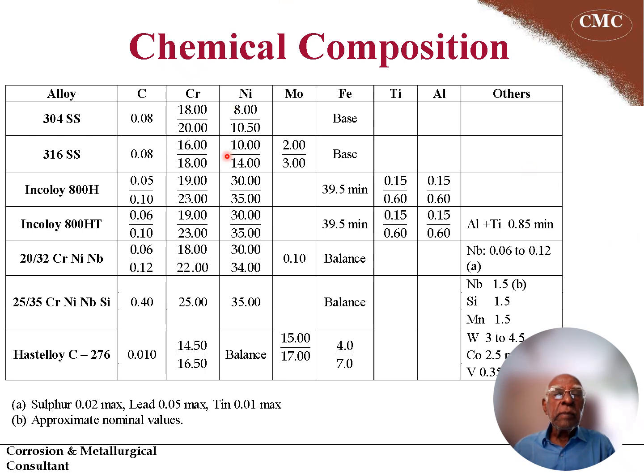The nickel is much higher. It goes up to 35% in specific alloys. And Hastelloy is basically nickel base. You can notice the intentional additions of molybdenum, up to 17% in Hastelloy, and special additions of iron, and also small amounts of titanium, aluminum, and niobium.